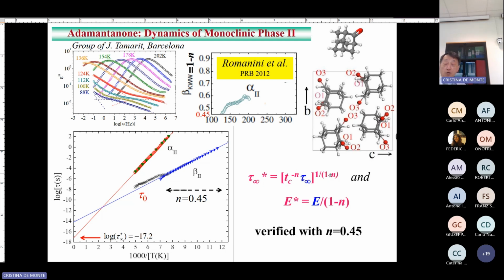Everything is known. No, I'm sorry. No, it's not known. So what you need to know is, from the alpha relaxation time, you calculate tau zero. You get two parts. One is the activation energy part, and the other one is the prefactor part. So both of them you can check with experiment. You can calculate from tau alpha all these quantities here. So from tau alpha, you can deduce this, and everything works out just as expected. So it's completely verified. I won't go through the detail, but both are verified. The connection is very nicely done.